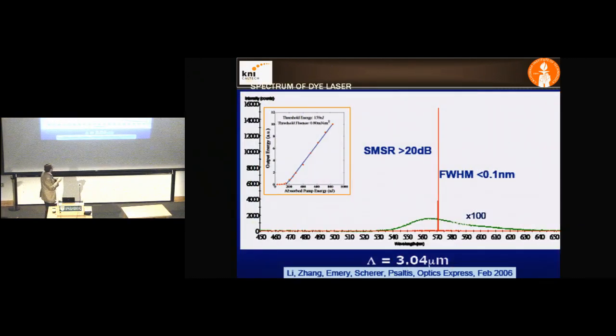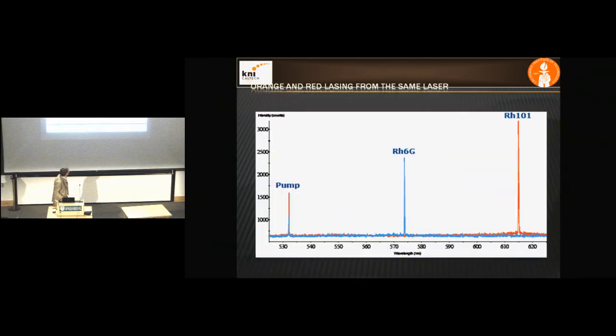And it has a certain wavelength at which the dye will start lasing. And that wavelength, in this case, is about 570 nanometers. It's because we use whatever the dye is. Okay? Rhodamine 6G gives us 570 nanometers. Rhodamine 101, a different laser dye, gives us the red, 610 nanometers, and so on.